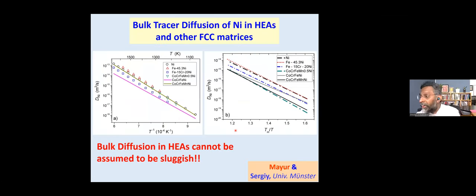And then you measure the diffusivities now. So one can do diffusion experiments. We have collaborated with our friends in Münster, and we are able to do what are called tracer diffusion studies, which give you certain diffusivity numbers. And these numbers, if you compare with the conventional alloys, you see that the diffusivities are not very much sluggish in nature, but the diffusivities are a little lower than what is expected in a conventional alloy. That could be one of the reasons why these alloys are thermally stable even at high temperatures.